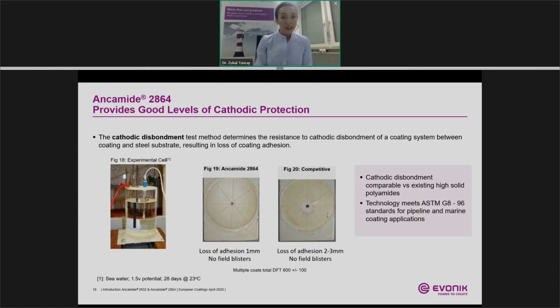In addition, while assessing the cathodic disbondment, we also see that 2864 provides excellent performance. In this example, we applied films of 600 mils and stressed them in a cathodic cell with 1.5 volt potential for 28 days at 23 degrees. Here we observed minimum creep and no blister. Based on these results, we can say that 2864 meets the ASTM G8 standards for pipe and marine coatings.